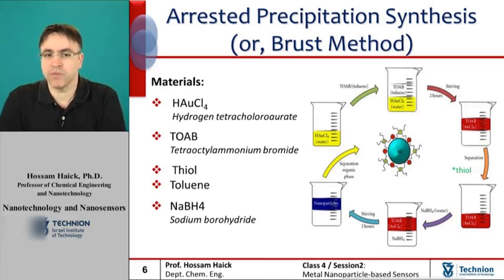The strategy of this method is the chemical bonding of a thiol ligand monomer on the surface of the gold nanoparticles during its formation. This reaction is referred to as attachment of self-assembled thiolated monomer, since it happens with no external help. The bond between the thiolated molecule and the gold surface is a covalent bond, which is extremely strong.